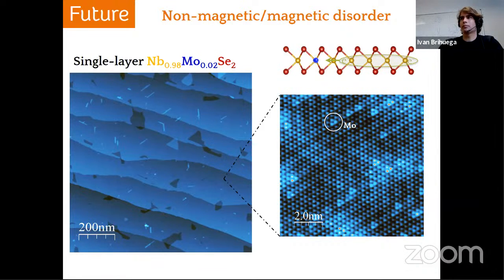Go. Okay. So, Miguel, thank you very much for this very good, interesting lecture. And I have the following question. The above gap resonances in conductance are well known long time ago. And usually they were related to the fact that electron hole pairs, Andreev type, for example, are confined in the superconductor or in some electrodes close to this superconductor. So actually, we also observe in our superconductors of 40 nanometer size above gap resonances. So how are your resonances specific for 1D superconductor and why is it not the same story as the above gap resonances well known before?